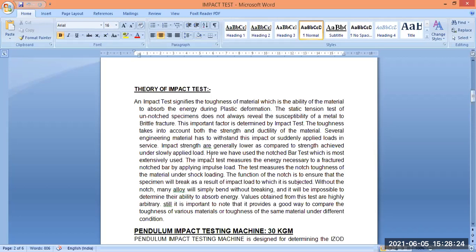Impact strength is lower as compared to the static approach, compared to the strength achieved under slowly applied load. Here we have to use the notched bar test, which is most extensively used. What we are using is a notched bar. I have shown you in the Charpy test, the bar has a notch exactly at the center of its length. In Izod, the bar also has a notch, but away from the central position.